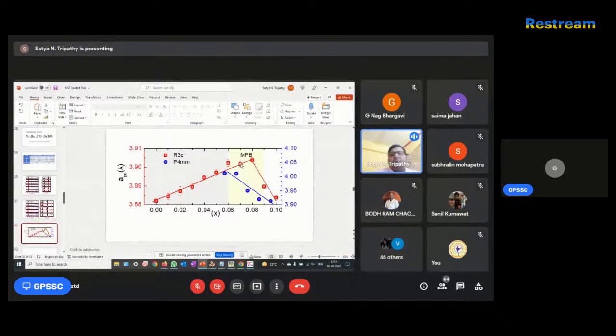Okay, you have the morphotropic phase boundary. The crystal symmetry of the sodium bismuth titanate is driven by barium titanate to a morphotropic phase boundary to give better ferroelectric, dielectric, piezoelectric properties. So if you have this kind of data, it will easily support your electrical measurements. So that is very important.